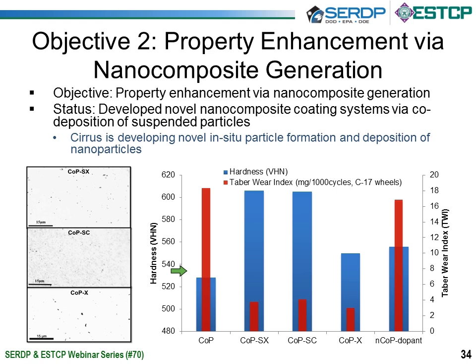The Taber wear test curve is in red and the hardness is in blue. So what we saw in all cases, the incorporation of particulate increased the hardness of the coating. And as well, we saw a decrease in the Taber wear from about 18 down in some cases to about 4. So we were quite happy with these results showing the benefit improvement.